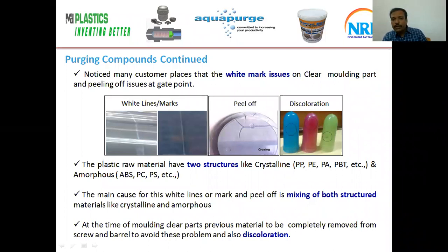See, at some customer places I noticed white lines, peel off and discoloration issues. Normally these kinds of issues are caused by mixing of two differently structured materials, such as crystalline and amorphous. To eliminate these defects, we have to completely remove the last processed material. Like PP to PC: if you change, PP is the crystalline structured material and PC is the amorphous material. So the crystalline material has to be completely removed from the barrel and screw prior to starting PC molding. Otherwise, white lines or peel off and those kinds of issues may come.